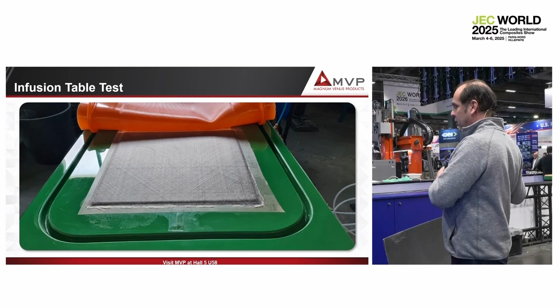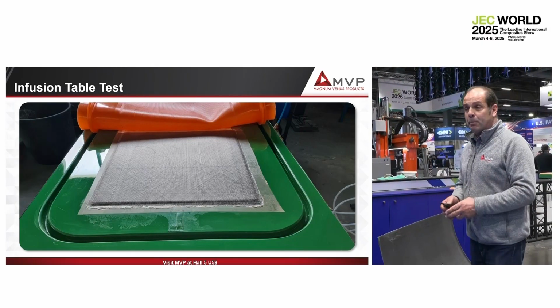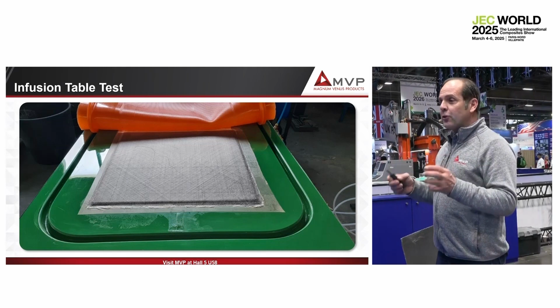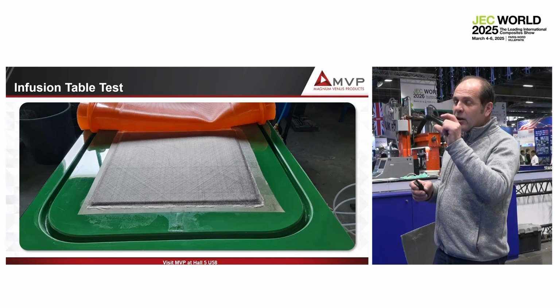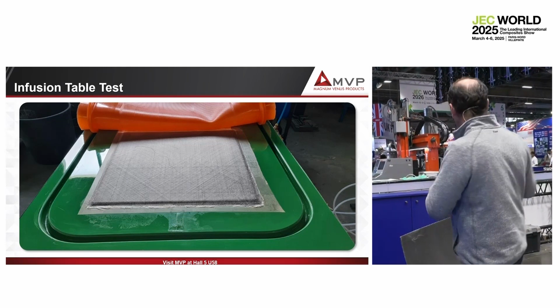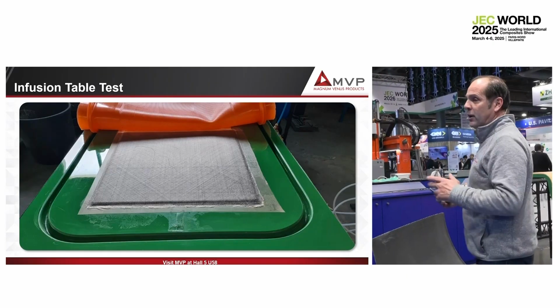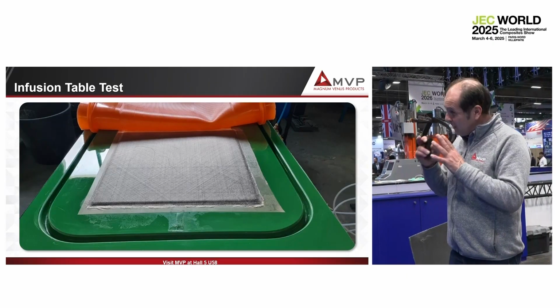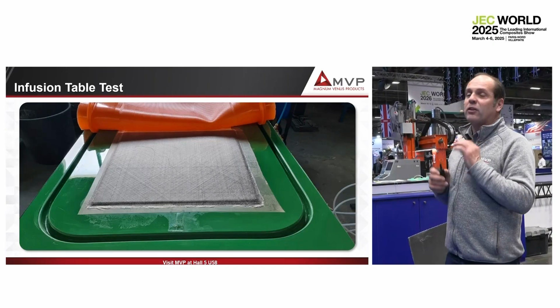Here we have a vinyl ester resin, but we also work with epoxy resin. Viscosity is not the same. We heat the epoxy and we get like 40 centipoise viscosity. Here we heat a little bit the vinyl ester resin and we have 100 centipoise. It's a little difference, but it can make a big change in infusion.